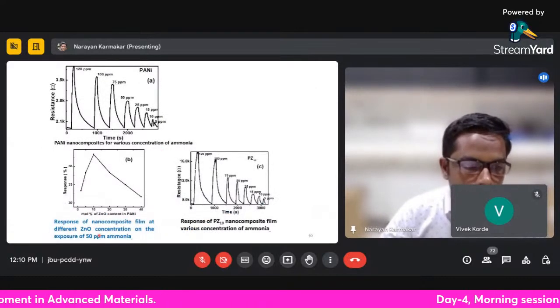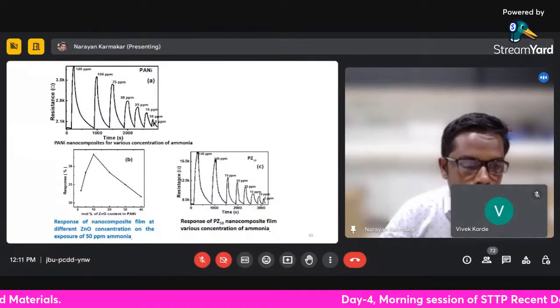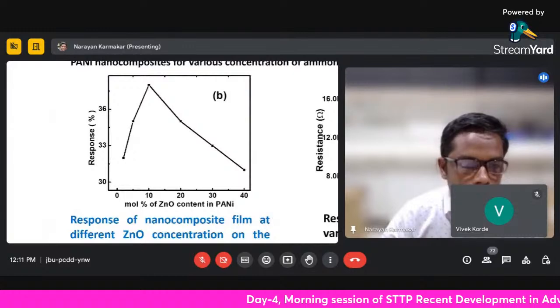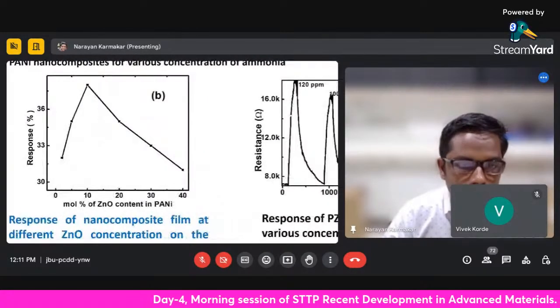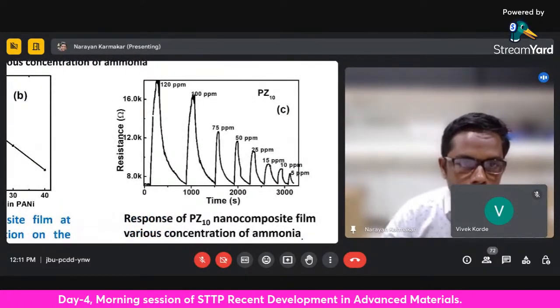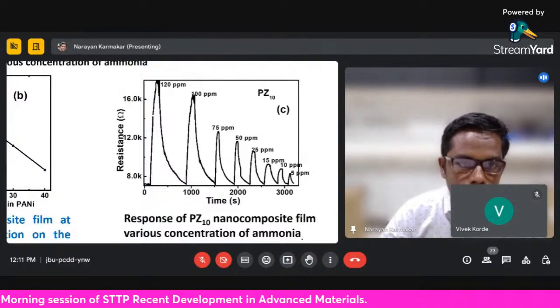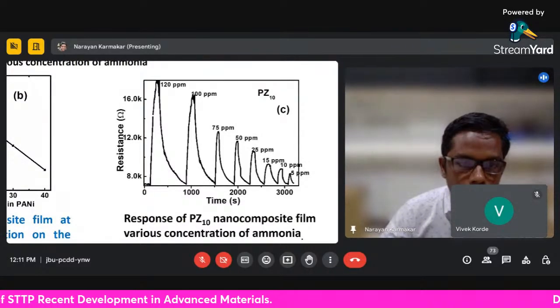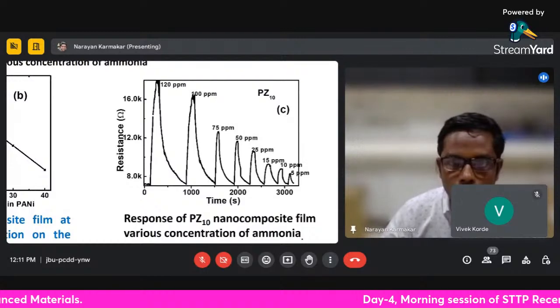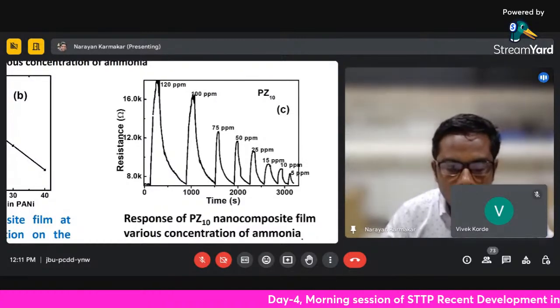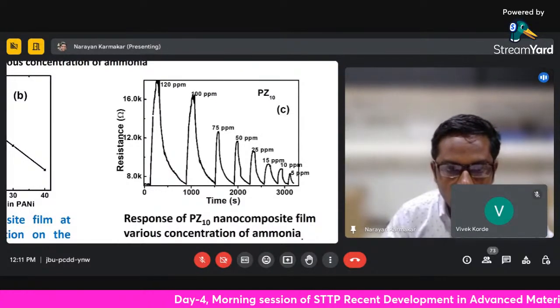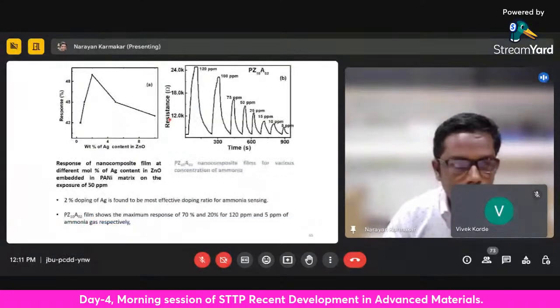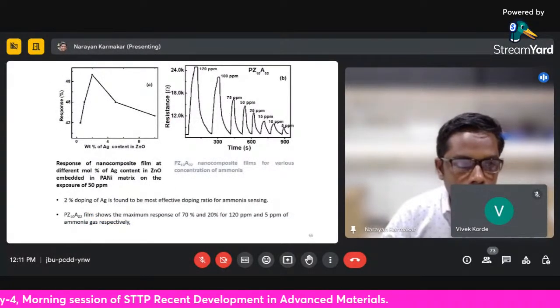So in that case, for this composite that is approximately 10%, that is PZ10, we studied a zinc oxide having concentration of 10%. We varied the concentration from 5 ppm to 120 ppm, and studied the behavior of the sensor for different gases.